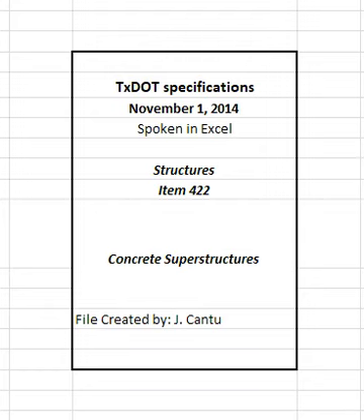4.6.10 Installation of dowels and anchor bolts. Install dowels and anchor bolts by casting them in place or by grouting with grout, epoxy, or epoxy mortar unless noted otherwise. Form or drill holes for grouting. Use only epoxy when installing horizontal dowels into the edges of slabs. Follow the manufacturer's recommended installation procedures for pre-packaged grout or epoxy anchor systems. Test anchors if required on the plans or by other items.